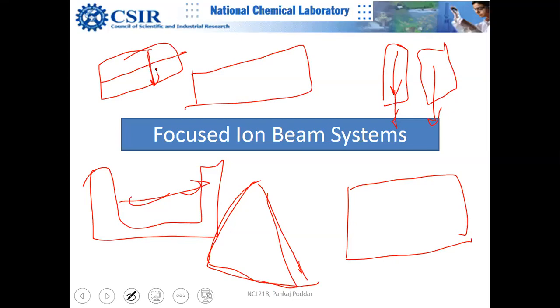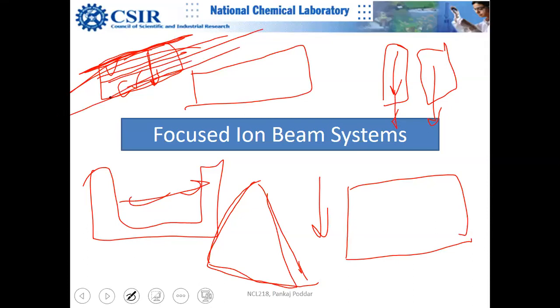For example, you have some specimen where you have more vanadium here and more chromium here. So how do you know the chemical composition depth-wise? What you do is you do the chemical analysis and topographic analysis of the top layer, remove it, do it here, remove it, and so on. So you can start peeling off these layers from the sample.